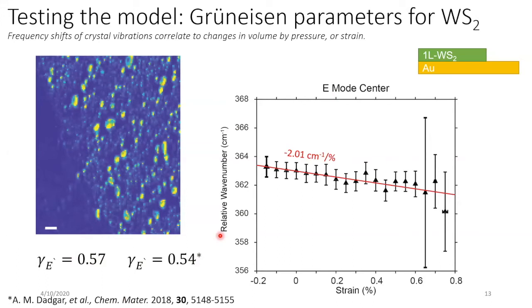The idea is you look for something called the Grüneisen parameter, which basically gives you a scale of how much a vibrational mode will shift for some amount of stretching. We can average them up to get higher signal to noise because actually the shifts of strain in TMD is very subtle, only like a few wavenumbers per percent. We can see how the mode shifts as the strain increases. We can fit a slope and compare it to what's been observed previously for other experimental techniques. It actually agrees quite well. So it seems to work. You can get a very good idea of what the strain is by just back-solving a very simple numerical recipe.